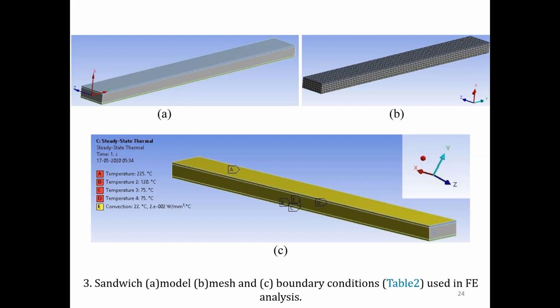a sandwich composite. And here the philosophy was, as we all know, that in conventional sandwich manufacturing, we manufacture the core separately, and then we prepare the sandwich by putting the skins at the bottom. We soak it in a thermosetting resin. We place it in a mold, and once the desired thickness of the skin is reached, we keep a core which is already manufactured by some other method. And then finally, we form the upper skin. Once the upper skin is formed, we close the mold. We keep it for 24 plus hours so that it cures. And then we take it out, we trim it, and we test it.